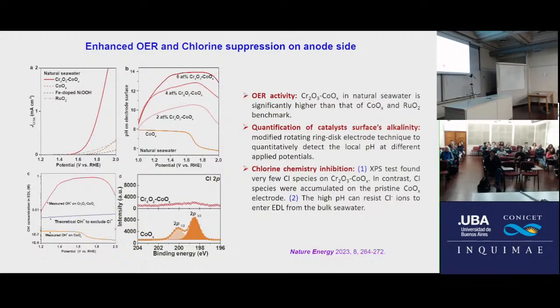Okay, so this one is the XPS results. We analyze the Cl 2p peak. You can see if we use CoOx only, we find two significant peaks, right? This indicates chlorine chloride is produced. However, for our case, this one, we never found that peak, right? This indicates in our case we never found chlorine chloride produced. Okay, one reason. So this one is the OH minus concentration on the surface, within several molecular distances. For our catalyst, you can see this concentration is very high. It means on the surface there is a lot of OH minus. They can reject Cl minus from seawater, reject each other, right? So chlorine cannot go into the surface. So for this reason, in our case, we never found chlorine chloride produced.